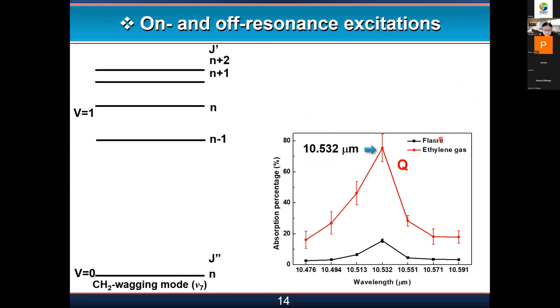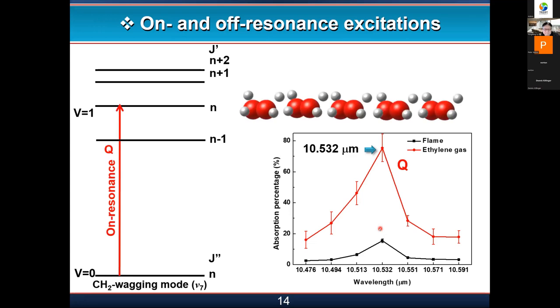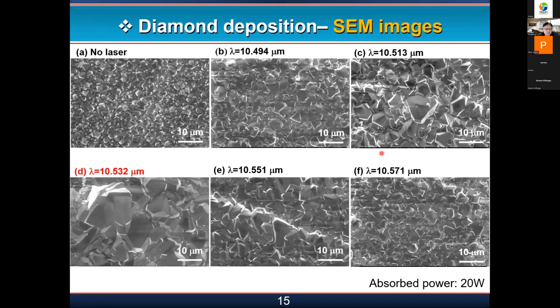Even in the combustion flame, there is still quite a portion of the ethylene molecules which are not burnt, not decomposed. So we can use laser to assist this process. There are different density of states at different rotational states, so we need to match the on-resonance frequency to have the best resonance. When we tune the laser wavelength to 10.532, we can see that the crystallinity improved a lot. Actually, the growth rate also improved a lot.